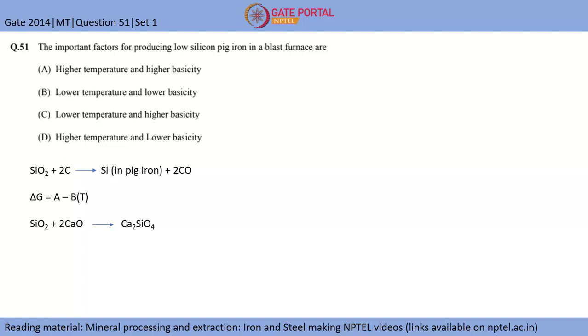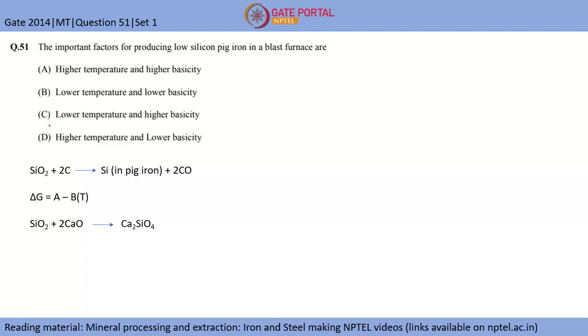And if you consider the second reaction, where silica reacts with lime, which as you know is highly basic, it will give rise to Ca2SiO4. So rather than this silicon going inside the pig iron, it will form a compound, Ca2SiO4, and it will join the slag. Hence you will have less silicon in your pig iron. Hence the correct option is option C, where the lower temperature is there to retard silicon in pig iron and higher basicity is required to form this compound which will join slag, and less silicon will be there in the pig iron. So the correct answer is option C.